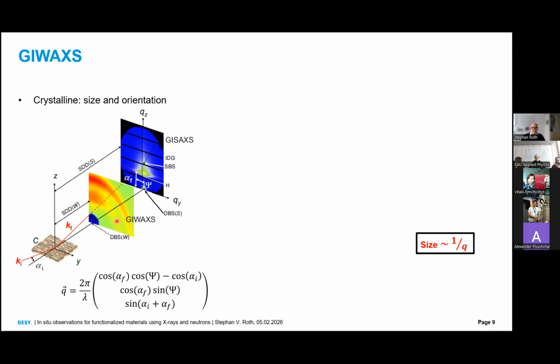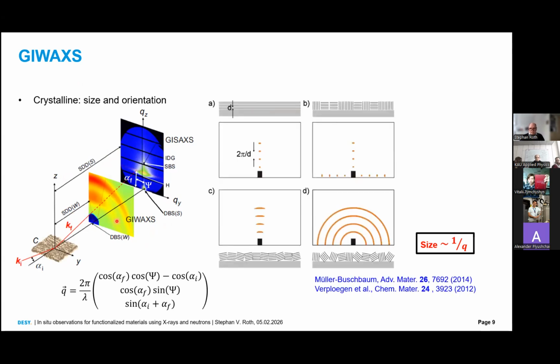You see the crystalline size and orientation, and this is highlighted here. If you have a layer by layer growth like this, very conformal, you see here Bragg dots, where the distance of the layers corresponds to 2 pi over d. You can imagine this as atomic layers, for example. When you have a certain mosaicity, like in this case orthogonally, you have Bragg spots in this and in this direction. When you have a slight tilting, you get arcs, and when you have more powder-like structure, you get these powder rings.